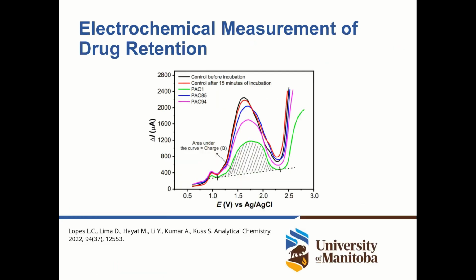Okay, and here you see a representative experimental plot of this experiment, carried out in differential pulse voltammetry. Here in black and red, you see our controls. The control in black represents a known concentration of tobramycin in our vial before we expose it to bacteria. In red, it is the same vial after 15 minutes of incubation, and you see there's no degradation in concentration of these molecules. Then we expose the solution to different bacteria strains.